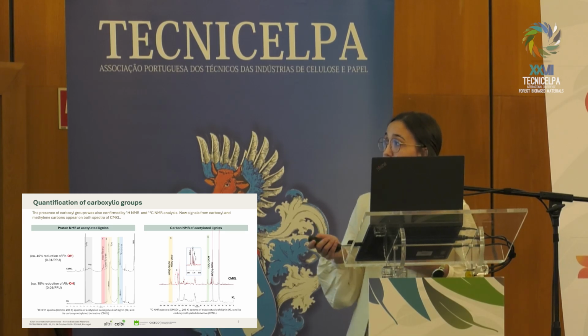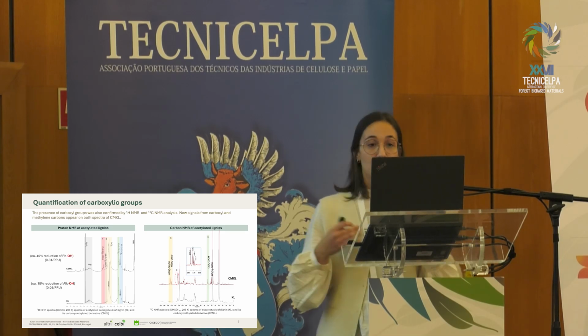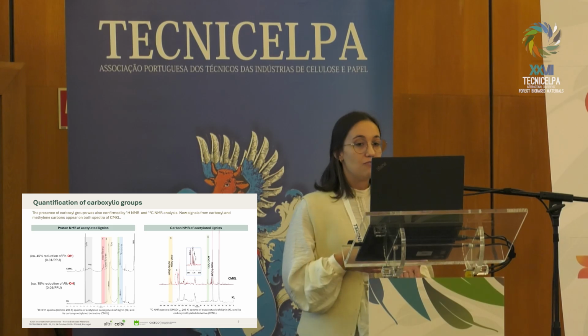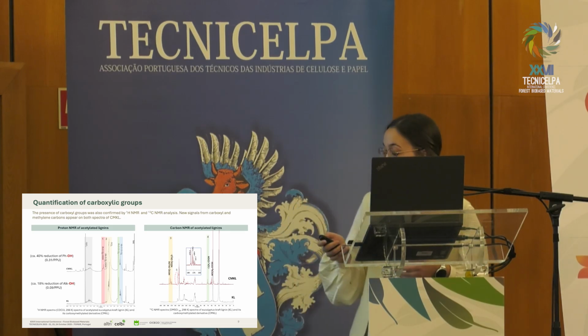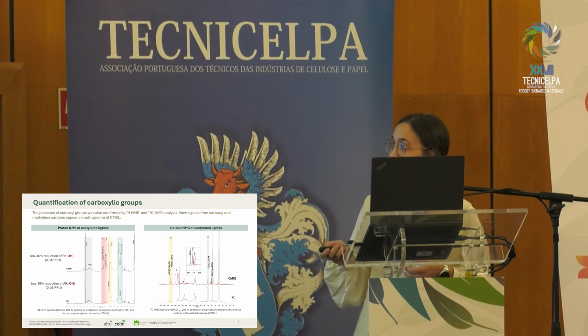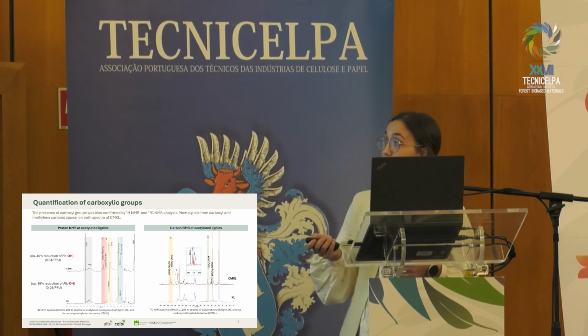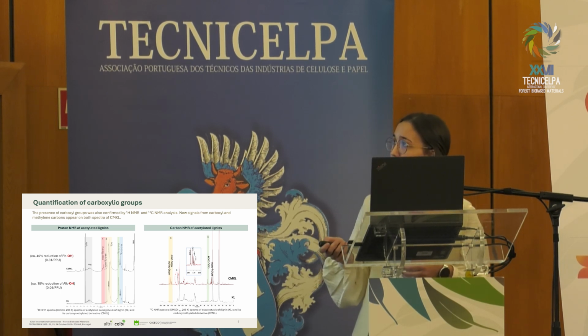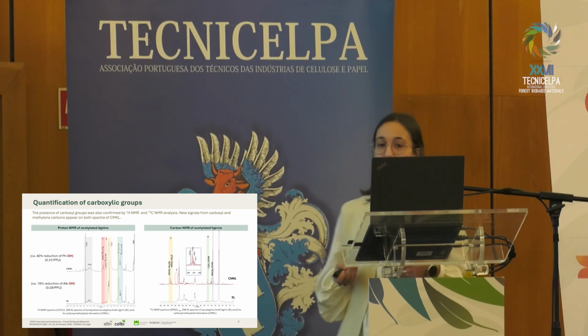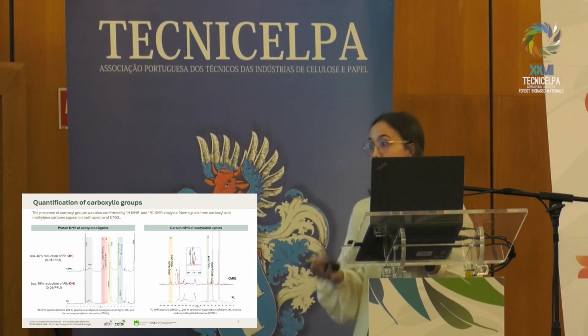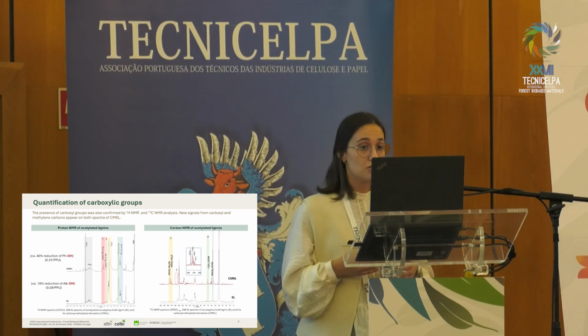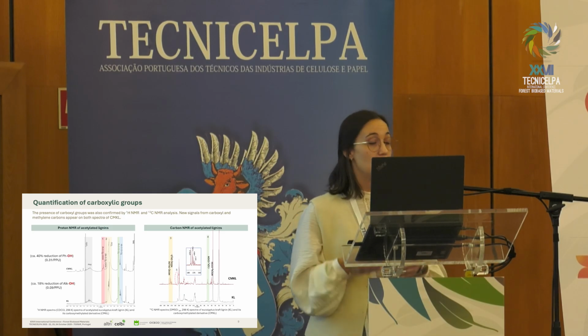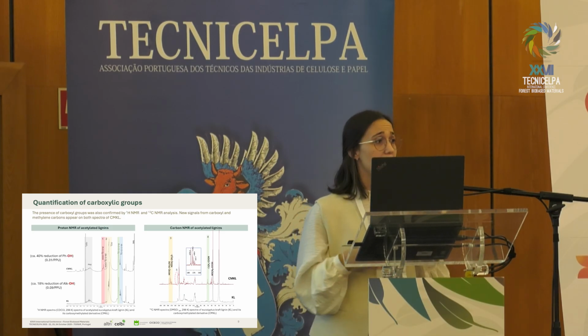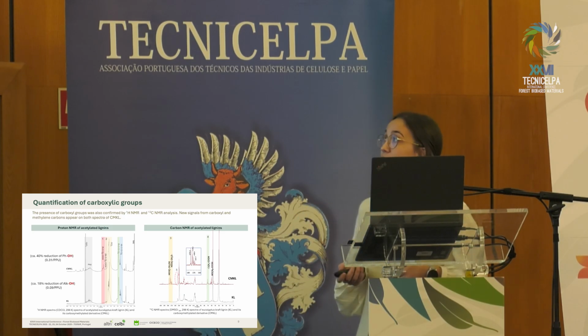Elemental analysis was performed to calculate this new empirical formula of phenylpropane units, where you can see these new carboxymethyl groups in here. But, okay, we have these new groups, but we also observed that the molecular weight is lower in the modified lignin. And this occurs due to the depolymerization of lignin under strong alkaline conditions.